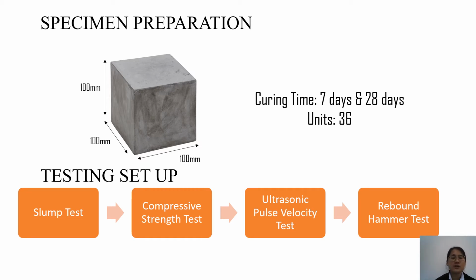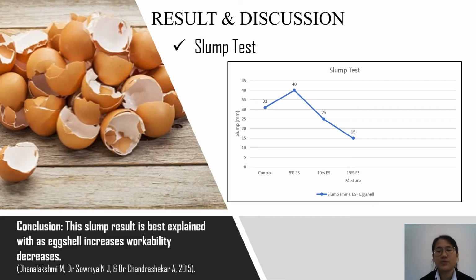Furthermore, we will conduct our testing such as slump test, compressive strength test, ultrasonic pulse velocity test, and rebound hammer test. Here we are going to discuss our results. First of all, slump test. Slump test is conducted to determine the workability of fresh concrete. From this result, we can know that the 5% eggshell concrete specimen obtained the highest slump compared to the control concrete specimen and the other percentages of eggshell replacement as cement. This slump result can be explained as: as eggshell increases, workability decreases.